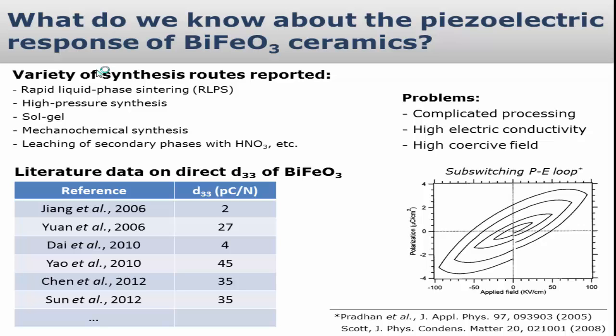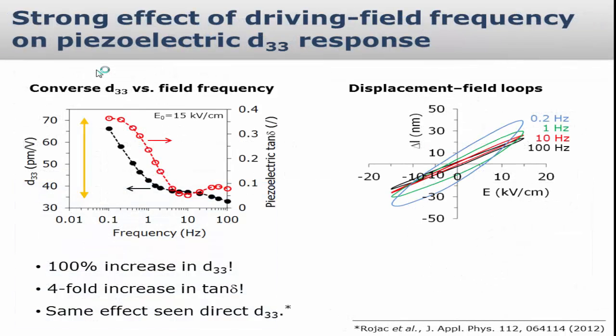You can see here, for example, a table where you can see a piezoelectric coefficient between 2 and 45, so there is a very large spread of data. This is known because BiFeO3 has a high coercive field, which is coupled to very high electric conductivity, and that's one of the main problems. Of course, also processing. What people usually report are the polarization electric field loops, a subswitching one, and I will show you that this sort of loops can also give you the one which relates mechanical and electrical variables, and can give useful information about how this material behaves piezoelectrically.